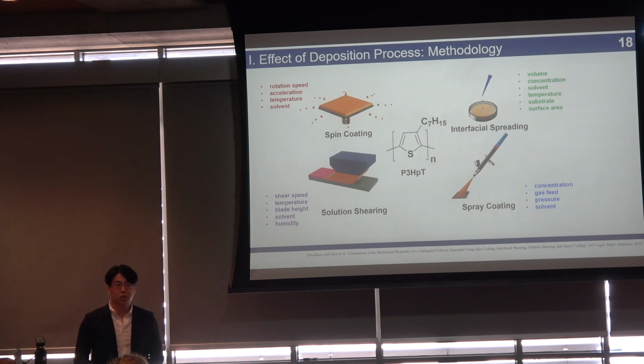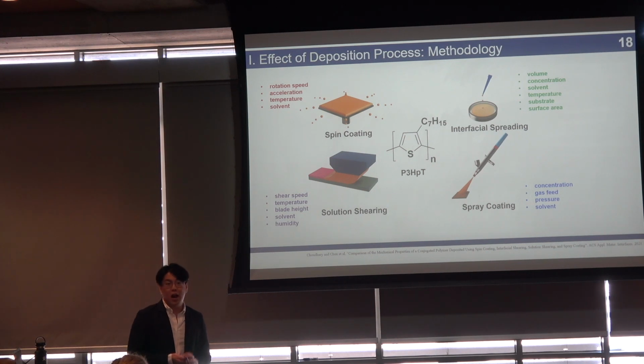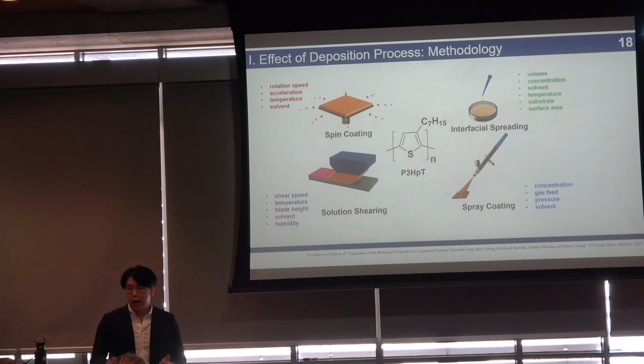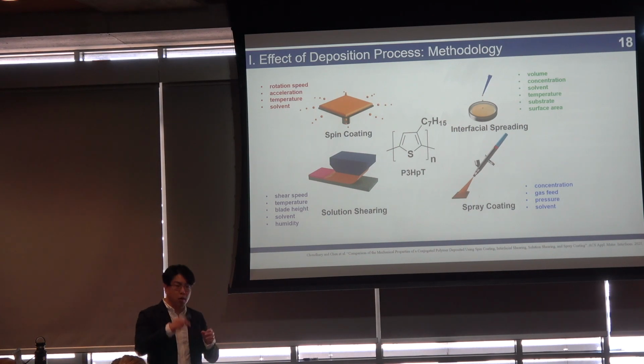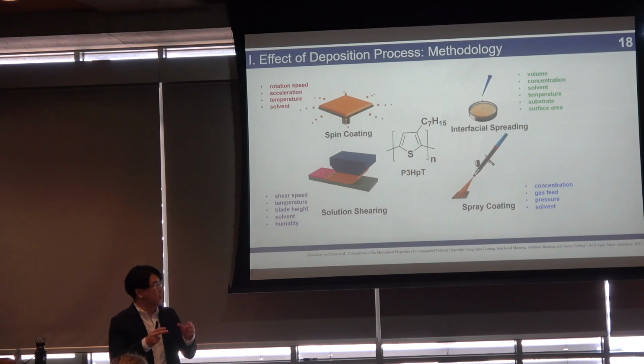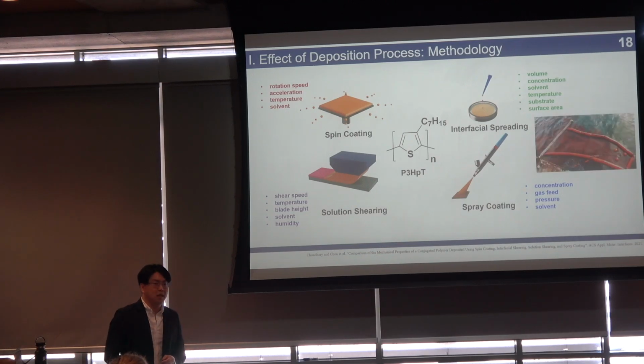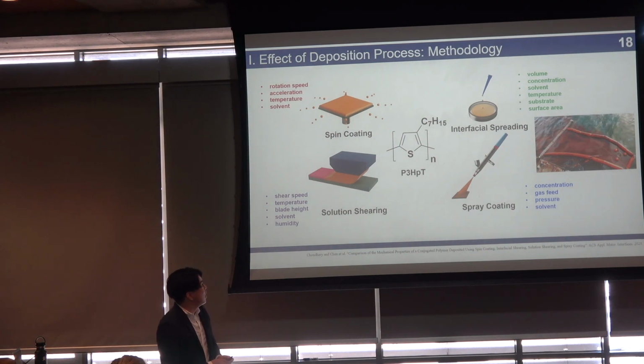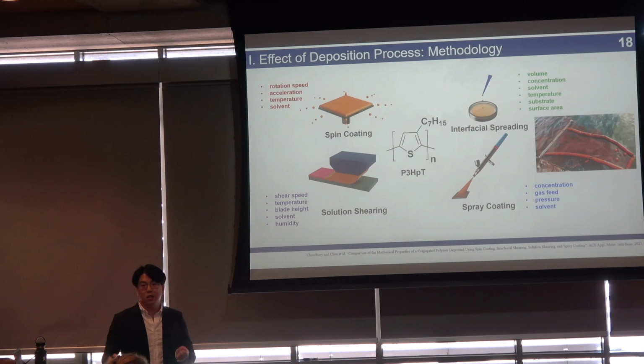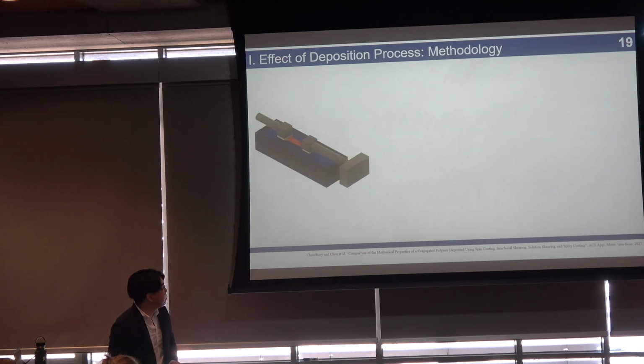What you can actually do is you can take advantage of the high surface energy of water, and you can drop the polymer solution on top of the surface water, and the film will actually naturally spread. You might think of this as, unfortunately, like an oil spill in the ocean. And you can actually take this polymer film and go do other things with it.